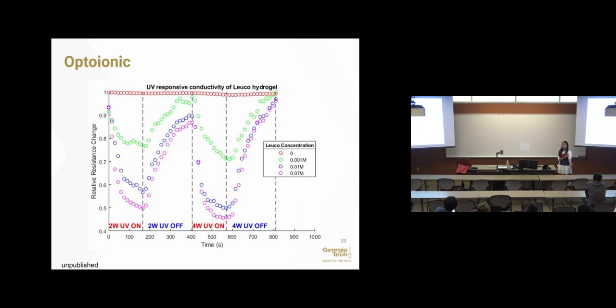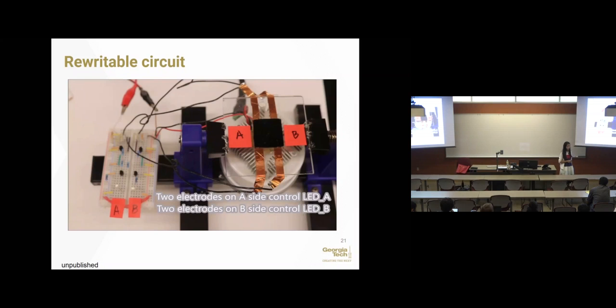Another thing we found is that using our gel, it's not just simply changing the molecule configuration or interaction with the solvent. It generates free ions. So we realized maybe this material can have a different electrical conductivity. Indeed, we tested without this functional molecule, and you see that whether the light is on or off, the resistance does not change. But with more of these functional molecules, once the UV light is on, the conductivity significantly increases, or the resistance significantly reduces. So it becomes more conductive. And it can recover, and it's reversible. You can do it many times.